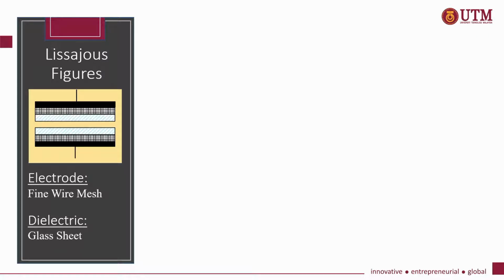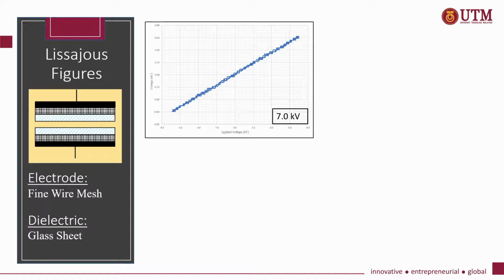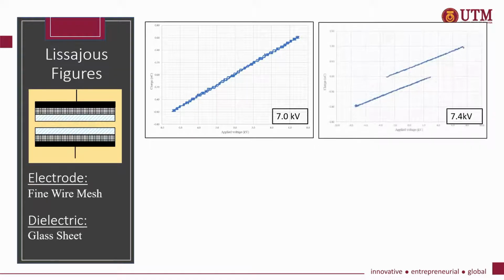So for the configuration with the fine wire mesh as electrode and glass sheet as dielectric, at 7 kV, the voltage across the gap is insufficient to cause the gas breakdown. So the voltage and the charge are in the same phase, and the plot of the Lissajous figure is a straight line. As the voltage further increased to 7.4 kV, the straight line slowly turns into an approximate parallelogram with only top and bottom sides, as shown in the second figure.